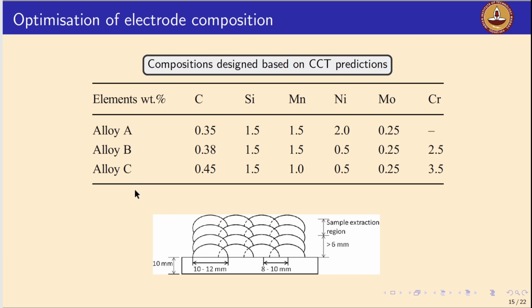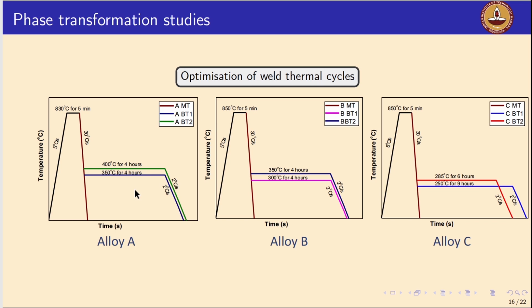How do we optimize the interpass temperatures and the subsequent isothermal bainitic holding time and temperatures when we do post-weld heat treatment? Based on the chemistries, we can carry out the dilatometry analysis to understand what temperature we have to hold at between the passes and during post-weld heat treatment. So the three chemistries I show you are alloy A, alloy B, alloy C. You don't need to worry about the actual chemistries. We just assume that we are looking at three steels: alloy A, alloy B, and alloy C.